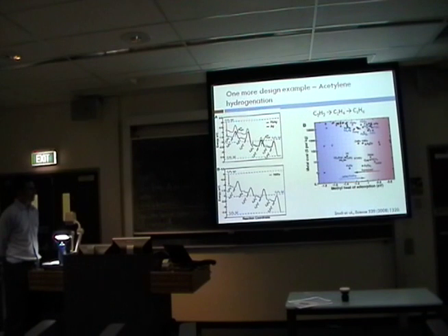Okay, and so again, in order to find an optimal catalyst, what these researchers did was track a key intermediate, and actually this isn't an intermediate in the reaction, but it tracks with the adsorption energy of intermediates in the reaction. And they can find sort of a sweet spot that's defined by this white box here that corresponds to sort of the ideal adsorption energy for this hydrocarbon type intermediate, the simple methyl intermediate. Right? And so they find that there are a number of materials in this box.